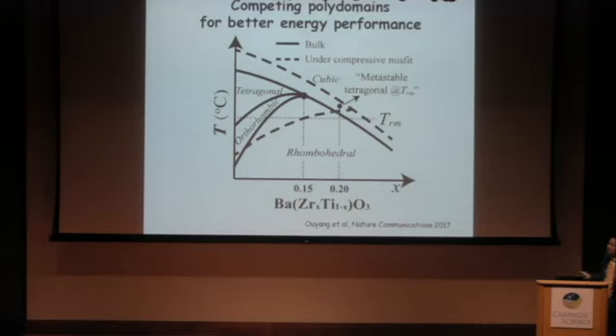In this case, I have the possibility of creating two types of polydomains. One is when the film is thin and the residual strain is very high: I can expect a tetragonal-rhombohedral mixed phase, just like in the case of bismuth ferrite. But when the film is thick or the strain is relaxed, I can expect some sort of rhombohedral-dominant microstructure, and hopefully I can have some of the higher-order polydomains. That requires that I grow the film really thick, not a few hundred nanometers, but into the micrometer level. So that's what we did experimentally.